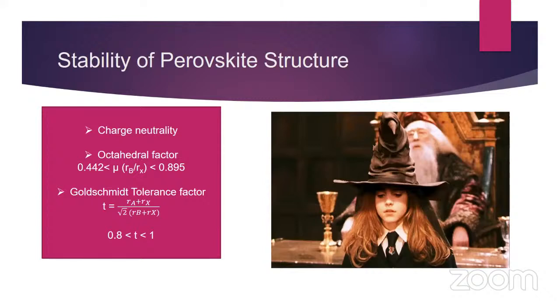The second one is the octahedral factor. Basically the octahedral factor is the ionic radius of the B cation relative to the ionic radius of the anion. You can see here, to get a perovskite structure, this value of mu should be from 0.442 to 0.895. And the third one is the Goldschmidt tolerance factor. Here is the formula of the Goldschmidt tolerance factor, where Ra, Rb, and Rx are the atomic radii of the A site, B site, and the X site ions.